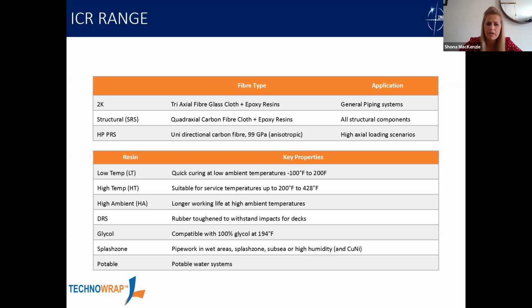We have a deck repair system. So as simple as it sounds, it's specifically designed for decks. Within that resin, there's a rubber toughened epoxy, which is suitable for withstanding impact. So it's good for lay down areas or foot traffic, walkways, things like that. So we wouldn't use our standard resin. We would look for something that's a little bit more ductile.